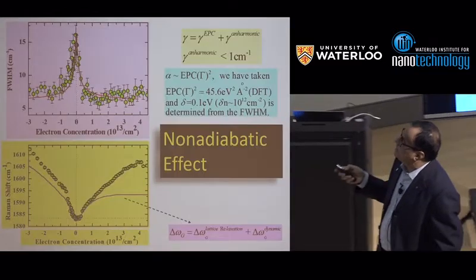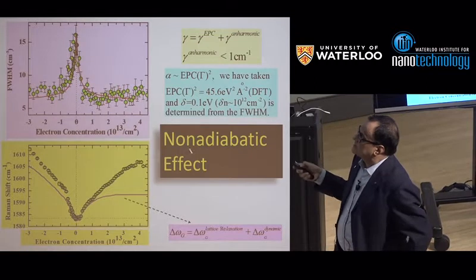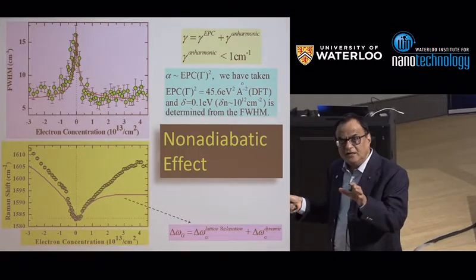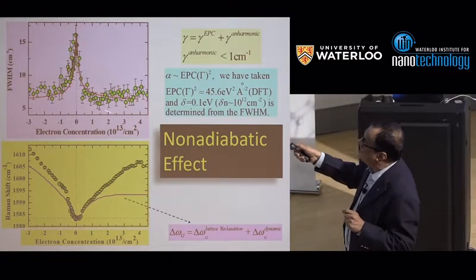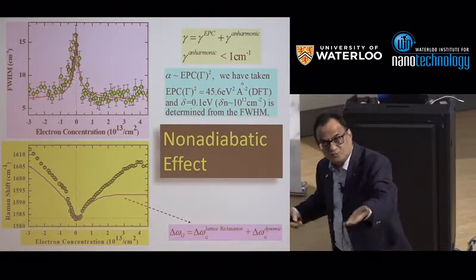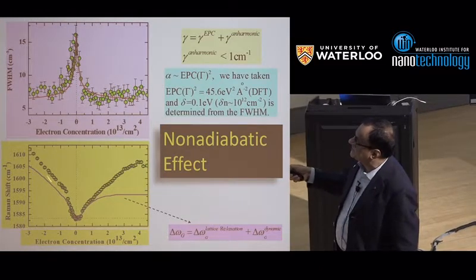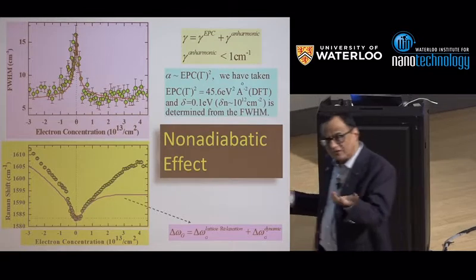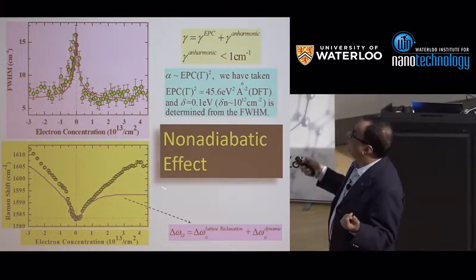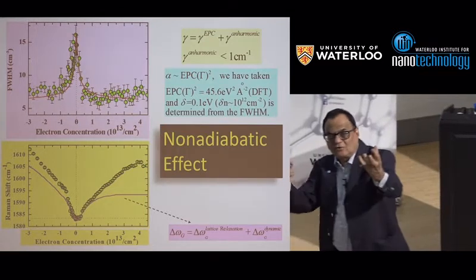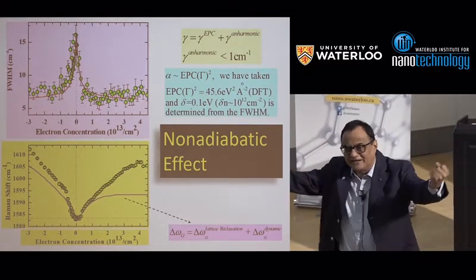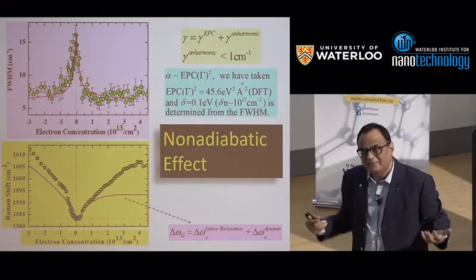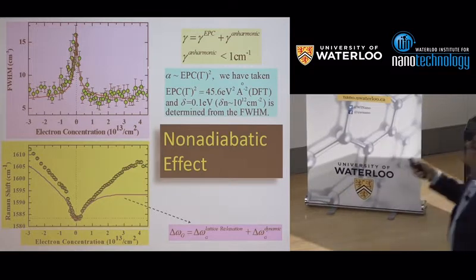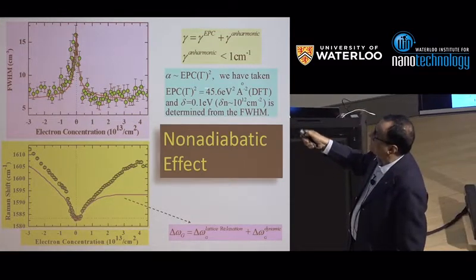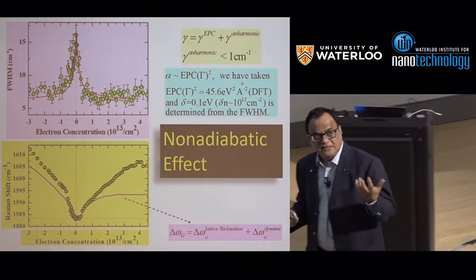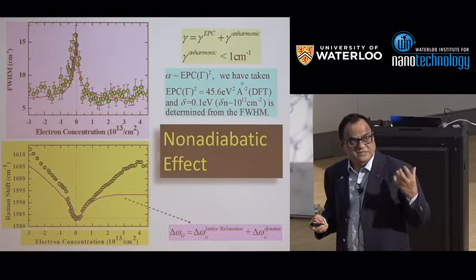So what we did at that time, we did a theoretical understanding of why such a thing is happening: why the line width is decreasing on doping and not increasing, which is what usually happens, and why the frequency is increasing and not decreasing on doping. This is a non-trivial effect. I will not go into detail. Graphene is a beautiful system where the electron and hole dynamics are coupled. They are not separated like in other semiconductors. So it is like a non-adiabatic effect. You put all that in the theory, and what you get is a quantitative estimate of the electron-phonon coupling parameter. And this is something very interesting, that Raman scattering can give you such detailed information.